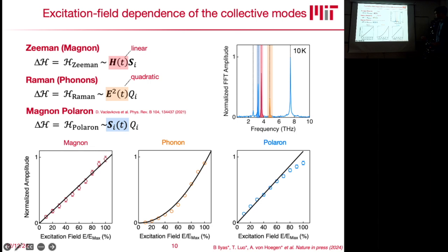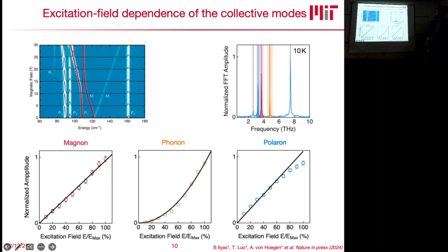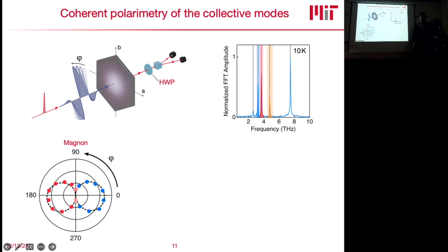And what we actually find is, in the beginning it scales linearly, and then it starts saturating. And I will come back to this in a second, but this is basically the transition from the magnonic behavior, which is linear, over to a more phononic behavior where it turns into a quadratic field. And in this specific case, the sign of the linear channel and the quadratic channel are of opposite nature. So they're basically destructively interfering. I will come back to this in a second, I promise. So this already shows us these are kind of the fingerprints of this hybridization, and we can pick them up in our measurement. And as shown here, this magnon-phonon in our case already shows that they're already hybridized at zero field. So this is an intrinsic property of the material which is not activated due to the magnetic field. It's always there.